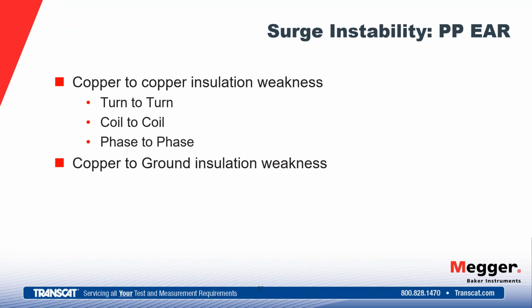Surge testing, again, we're looking for stability of this waveform as we pulse the motor under test. We get that turn to turn, or coil to coil, phase to phase. We're looking at copper, possibly copper to ground insulations. If that happens on the early turns, we can see that with the surge test.